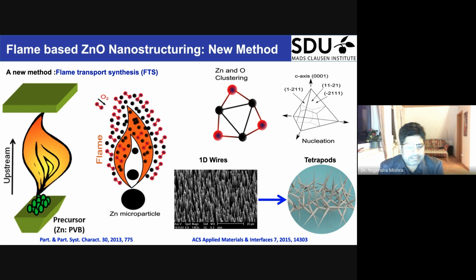The question is why zinc oxide? Usually it is a common belief in the community that for zinc oxide almost everything is done. There is nothing left. And I started my research with zinc oxide because there were around 2 million papers available. The beauty of zinc oxide is that it has a hexagonal wurtzite crystal structure. That means it doesn't matter whatever process you follow, you mix zinc acetate with any solution in your kitchen, and you will easily end up with some kind of 1D structures from nanoscale to microscale, depending on whatever you are following. So that means it offers easy 1D growth because of crystal structure and surface energy minimization. And it was also a motivation that I have been using at that time.